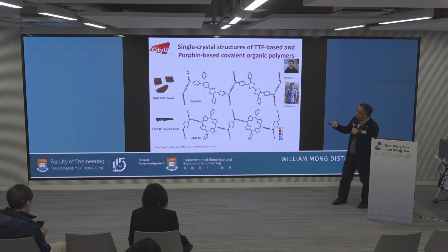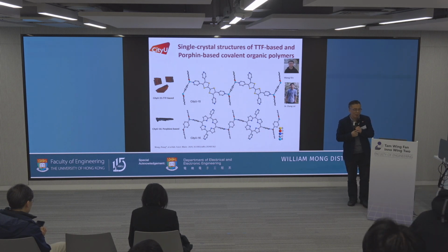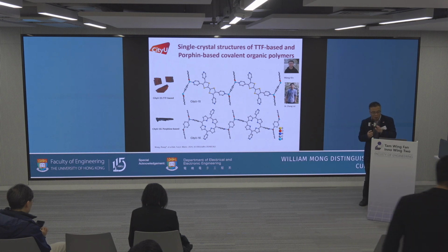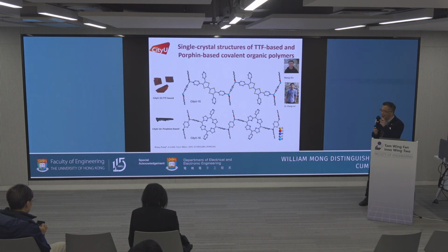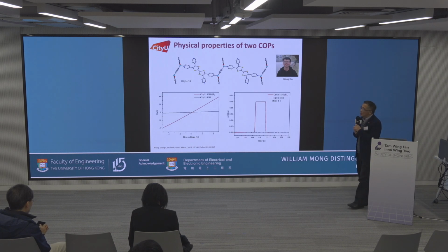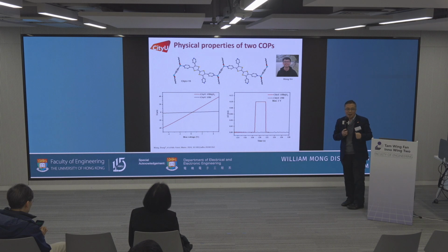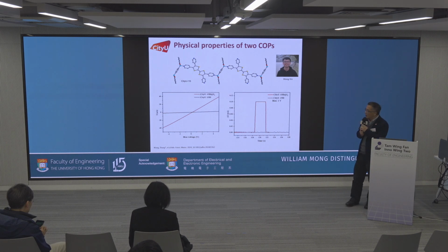But one thing I tell you: look at this boron ester species, these two pyridines are in a cis structure, rather than a trans structure. This is very important. Why I mention this is that later our idea keeps going, and you will see this conformation change. Since we have TTF in our polymer, we want to look at the conductivity. Initially we just take the single crystal and look at the conductivity. You can see it is almost insulating, and after iodine doping, the conductivity increases and it becomes a semiconductor.